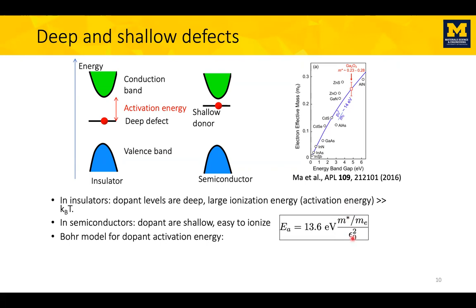The dielectric constant is 10, so 10 squared is 100. So 0.1 over 100 gives you a factor of 1 over 1,000. And that's how you get about 10 milli-eV for the activation energy of dopants in semiconductors, right? Order of magnitude 10 milli-eV.